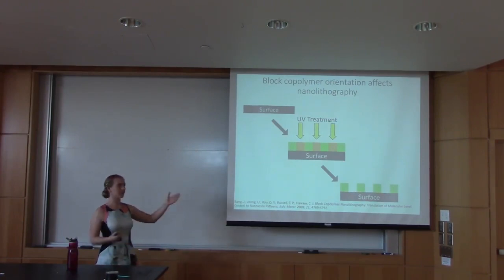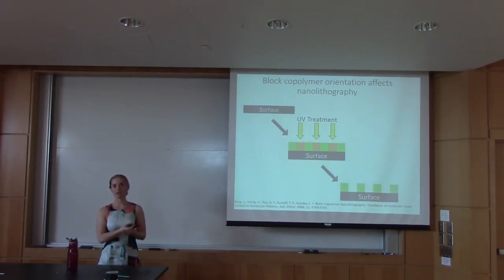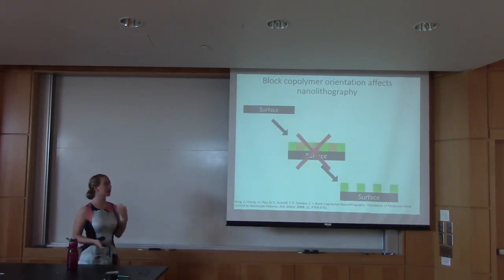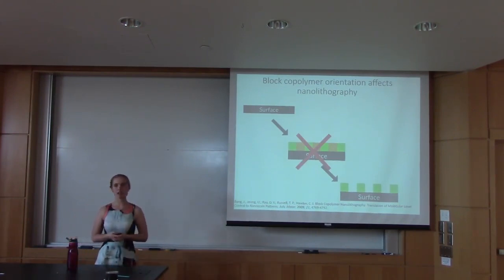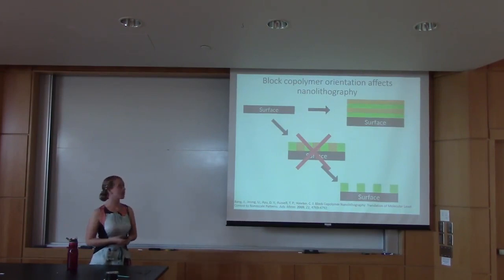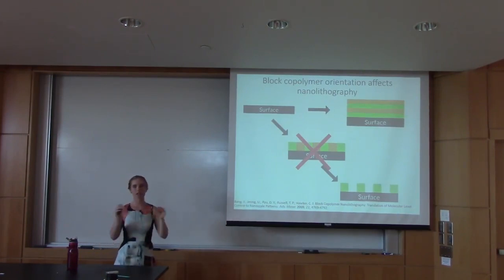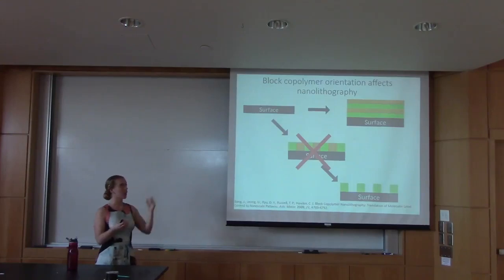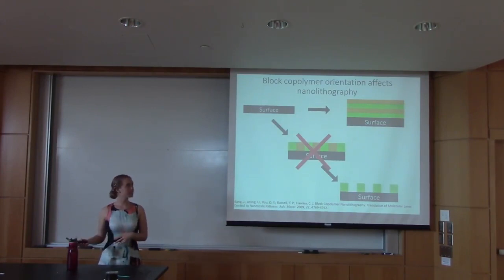So it looks really simple and like, why would we even want to do this? But this is just the simplified side-on view versus that top-down view, which is a much more complex pattern. And where my research comes in is the fact that this does not occur. Instead of getting this perpendicular orientation of the block copolymer to the surface, we get this parallel orientation. And we can't use that because if we apply the UV rays, it's only going to degrade that top orange layer preferentially, and it's going to leave the rest of it. So we don't get a pattern that we can use to pattern our circuits.